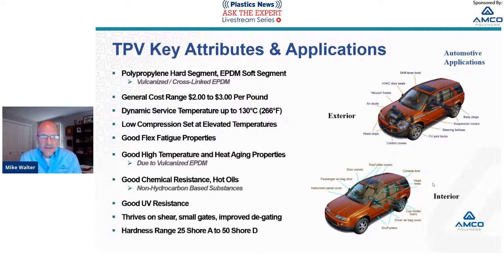Along with it, TPVs have pretty good chemical resistance, mainly to hot oils. TPVs stand up primarily to non-hydrocarbon-based substances. They also have really good inherent UV resistance. And one unique feature of a TPV is that they thrive on shear. So if you're injection molding TPVs, you can use really small pin gates. It improves your degating, gives less gate vestige, and of course, overall better cycle times. The hardness range for TPVs is a little less generous than SEBS, but it's 25 Shore A to 50 Shore D.